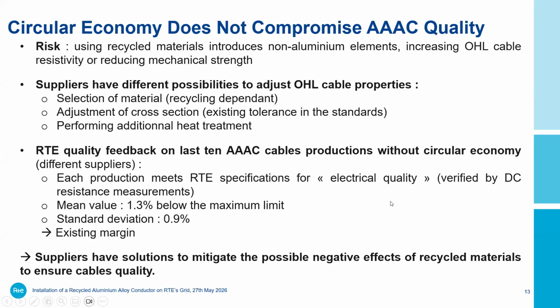We also looked at the quality data we have for the overhead line cable production. We asked our suppliers, so this data is not only for one supplier. We make a mix of different suppliers. What we see is that each production meets RTE specification for electrical and also mechanical quality. We verify with resistance measurement. We have some mean value quite below the maximum limit. So we see that on the production we make for RTE, the cables are quite good and quite below the maximum value, and we have quite a low standard deviation.